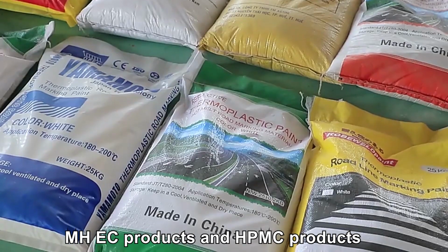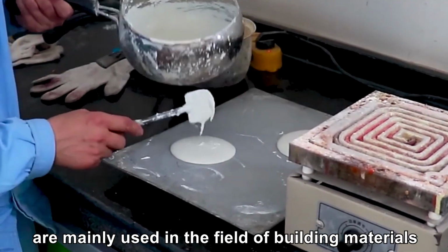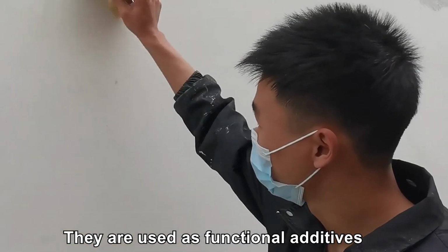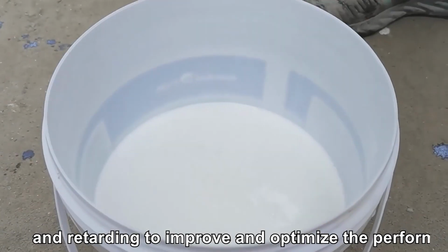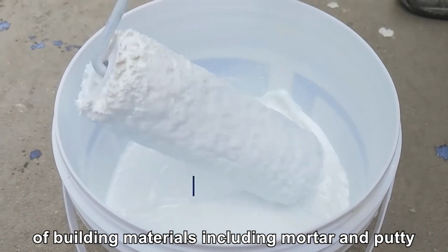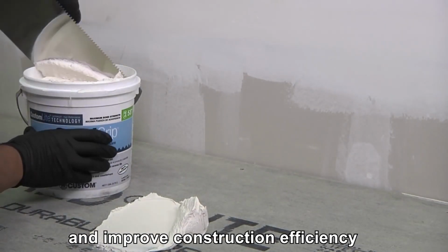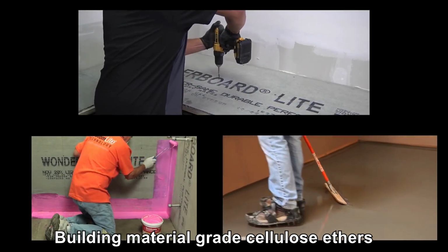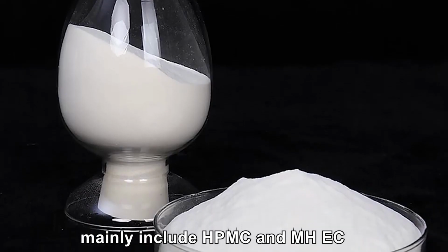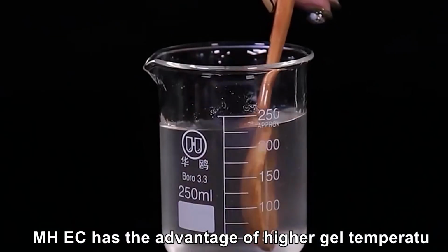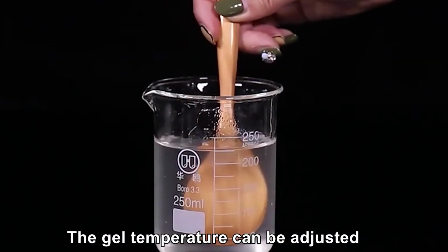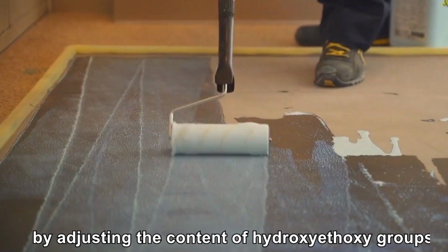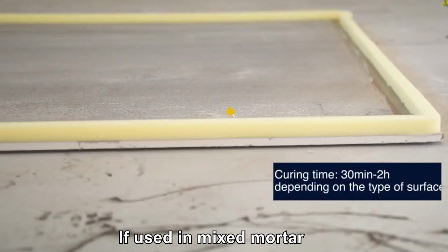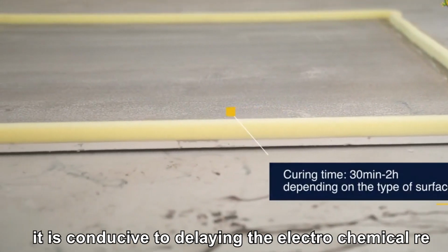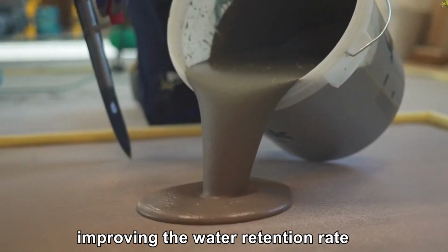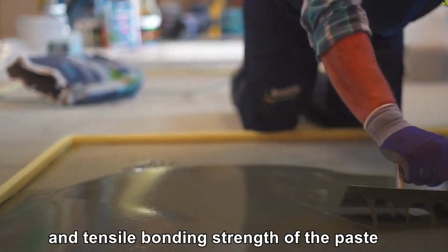MHEC products and HPMC products are mainly used in the field of building materials. They are used as functional additives, such as thickening, water retention, and retarding, to improve and optimize the performance of building materials including mortar and putty, and improve construction efficiency. Building material grade cellulose ethers mainly include HPMC and MHEC. Compared with HPMC, MHEC has the advantage of higher gel temperature. The gel temperature can be adjusted by adjusting the content of hydroxyethoxy groups. If used in mixed mortar, it is conducive to delaying the hydration reaction of cement paste at high temperatures, improving the water retention rate and tensile bonding strength of the paste.